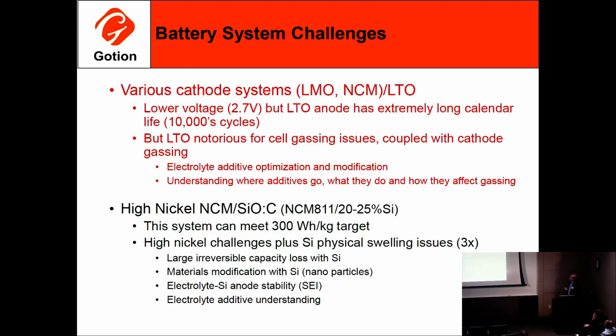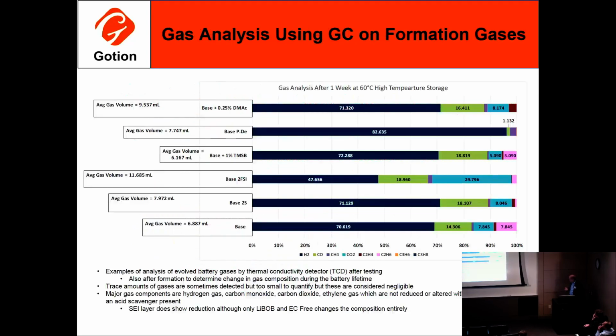You couple that with the swelling that you get on the cathode side from the NCM, and your problems keep multiplying. But you can make some modifications to the LTO powder itself, from doping and coating and things like that, and you can also look at electrolyte additives to improve that. An example of that is here. On this chart, we're looking at our baseline on the top line. The length of this white bar is proportional to the amount of gas formed. You can basically cut it in half by putting in the right amount of additives.